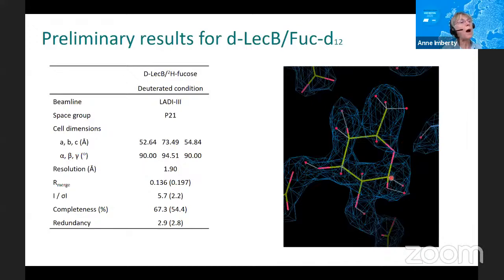I just want to show you how complete this neutron map is. There is no cancellation, because all the deuterium on carbon here is perfectly seen in the neutron map. And we have excellent density continuation for the hydrogen bond between the aspartic acid here and here on the fucose. So from this, we will have more details, and I'm looking forward to seeing the effect of the calcium ion on the position of deuterium and what will happen.